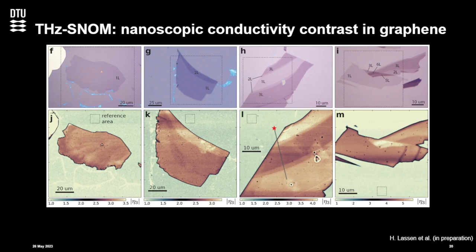The interesting thing is it works. These are light microscope images — high contrast, so you can see the number of layers based on white light interference. And these are the terahertz images recorded with the system. This is a monolayer — one layer, two layers, three layers, and some combination. We can clearly see whether we have one layer or two layers or three layers. Even within the monolayer, you can see erosion-like features showing that even within the monolayer there's a clear variation of the contrast.